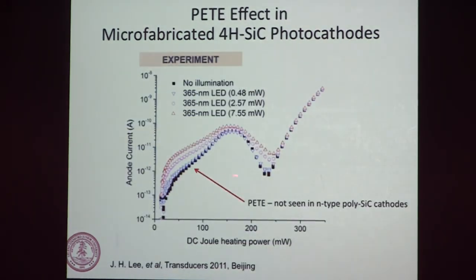And lo and behold, we have some experiments. This is a log scale. Obviously, the currents are very small. There's no integrated anode. The anode is centimeters away in this vacuum system. But we're seeing photon enhancement that's not associated with heat. I'm not going into the details on that, but we have a blue LED that's not heating, shining photon flux into the cathode, and we're getting this very nice demonstration of enhancement in a microfabricated photocathode.